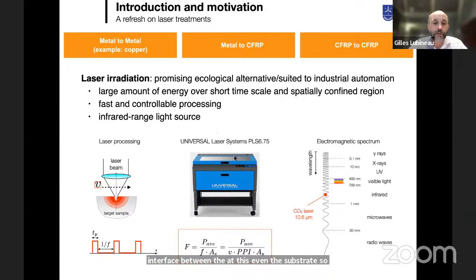I guess everybody here is very used to laser treatment. What you do is take a laser beam, and this laser beam is going to introduce a high density of energy on the surface, and depending on the wavelength, you can get different types of results. So here, for all demonstrations, we are using a CO2 based laser with a 10.6 micron wavelength.